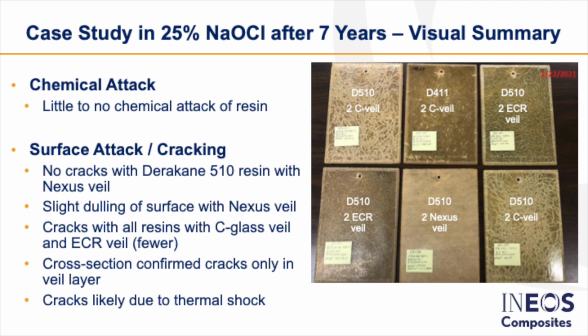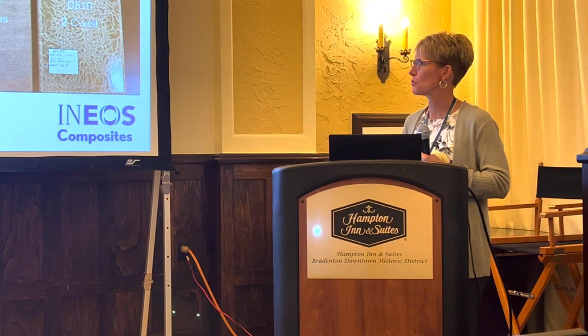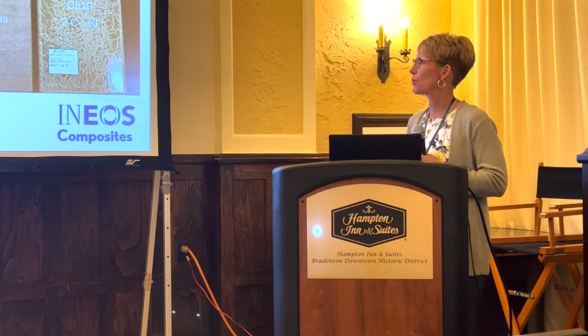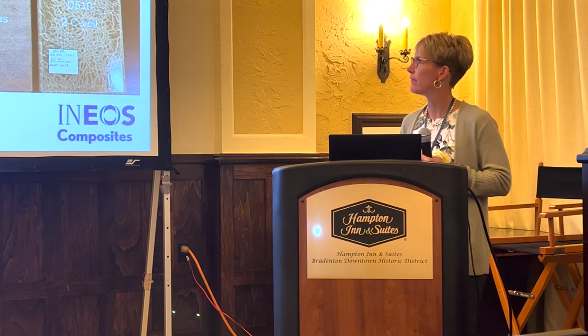Really, most of them, there was very little chemical attack or change in the surface of the coupons. Some were slightly duller than others. Essentially, with the 510, there was very little cracking with the synthetic veil. And as I mentioned, we were able to determine by looking at the cross section that the cracking was really due to some thermal cycling as opposed to any chemical attack.